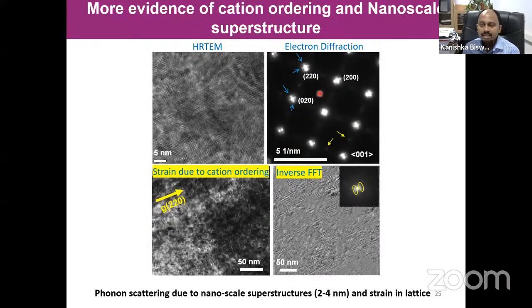Then we see not only this halfway spot, we see a superstructure spot, a very nearby spot. So that tells that basically there are nanoscale superstructures in this compound. So then more careful TEM analysis shows that we have ripple-like structures. This is called strain ripple, which is observed in many materials in the metallurgy field. So these strain ripples are nothing but telling that these materials are highly strained. So these strains are also good to actually decrease the thermal conductivity.